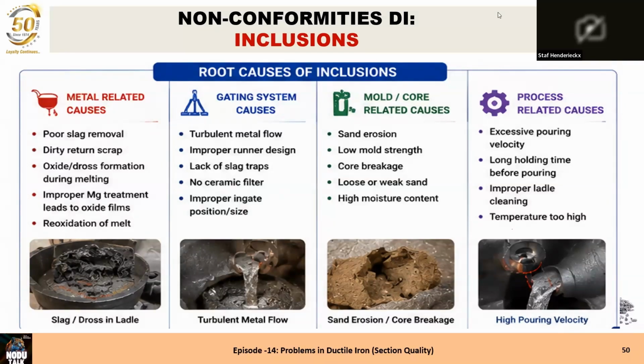If there is some slag against the ladle wall and you tap in new metal, the slag will come loose, and it will enter the metal and eventually also your casting. And a high temperature, of course, because the higher the temperature, the quicker the sand will be attacked, the more the dross will be formed. High temperature is always a negative thing.